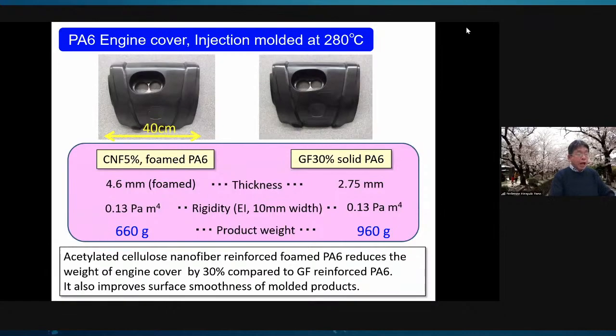These are engine covers of automotive produced by injection molding at 280 degrees Celsius. Cellulose nanofiber reinforced foamed polyamide 6 reduces the weight of the engine cover by 30% compared to glass fiber reinforced polyamide 6, while keeping the same rigidities, because the foaming increases the thickness around 1.5 times.